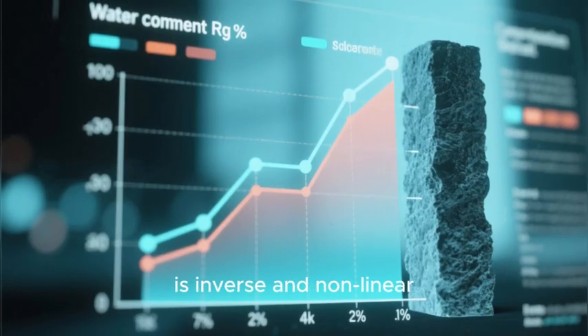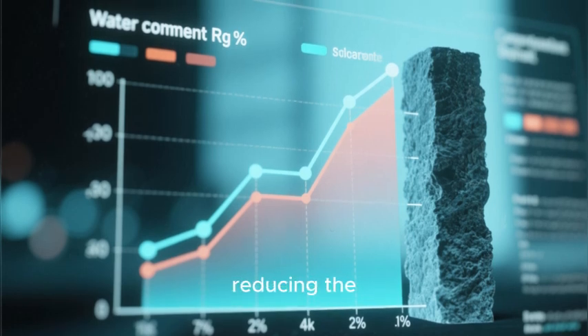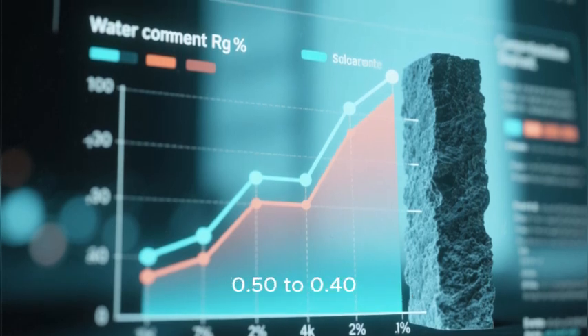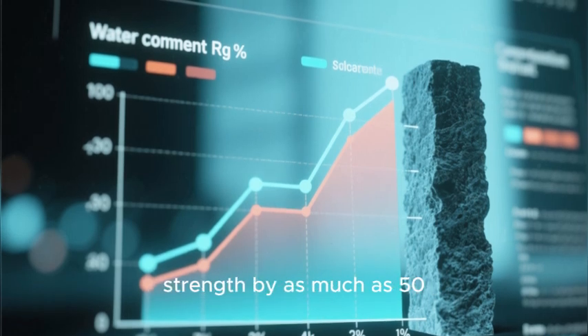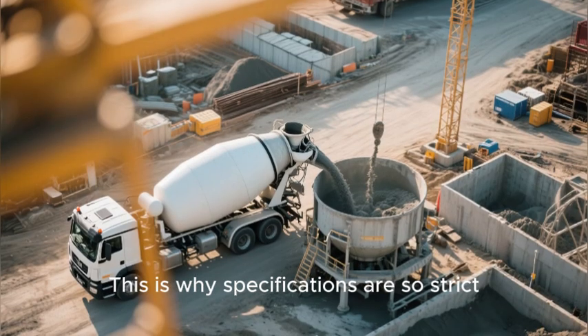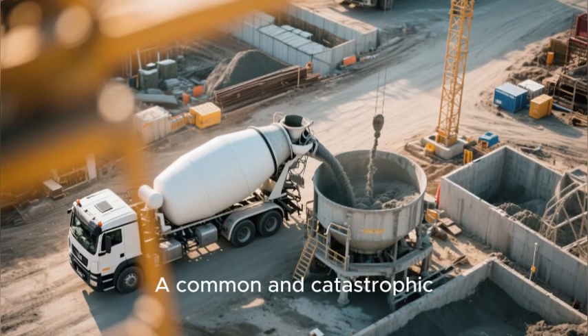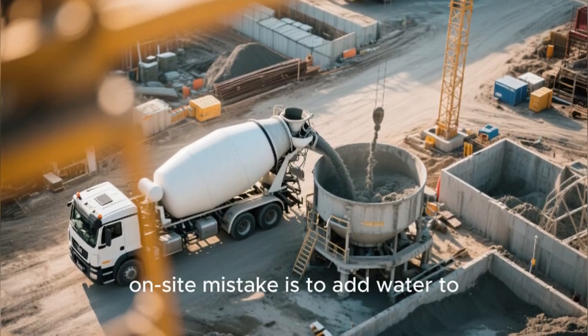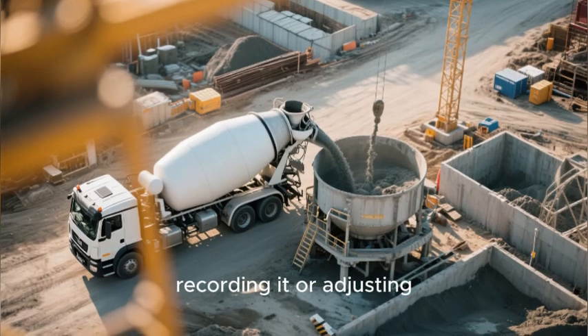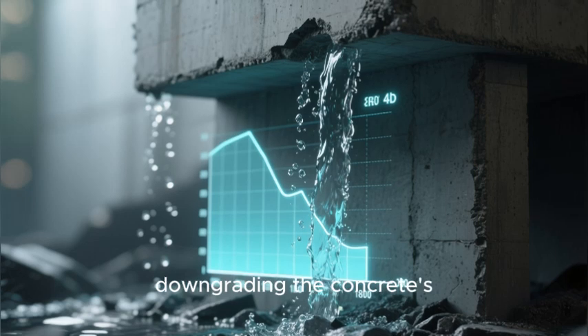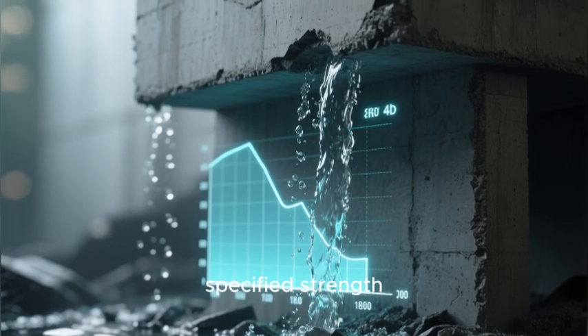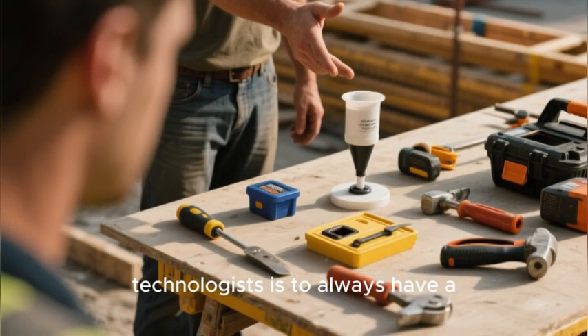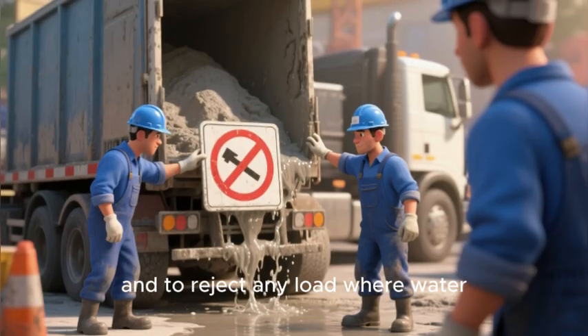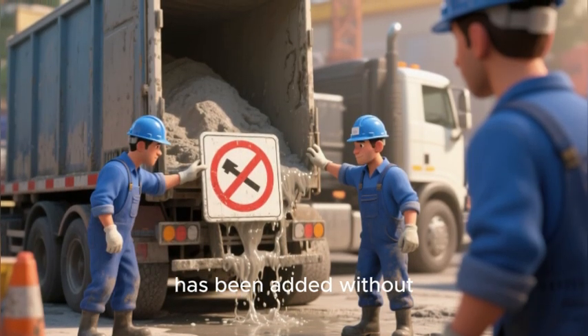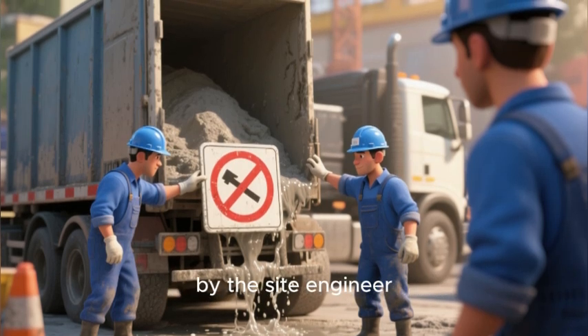The relationship is inverse and nonlinear. For example, reducing the water-cement ratio from 0.50 to 0.40 can increase the compressive strength by as much as 50%. This is why specifications are so strict. A common and catastrophic on-site mistake is to add water to increase slump without recording it or adjusting the mix design. You are not just making it easier to work with, you are mathematically downgrading the concrete's specified strength. A pro tip from concrete technologists is to always have a slump test kit on site and to reject any load where water has been added without authorization and recalculation by the site engineer.